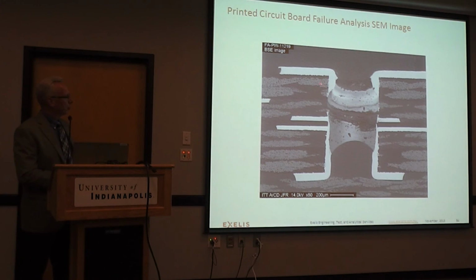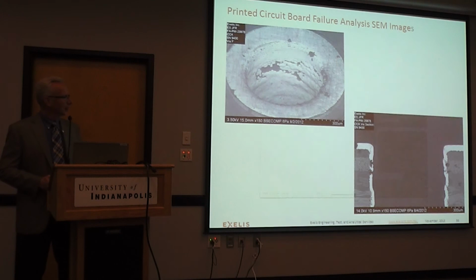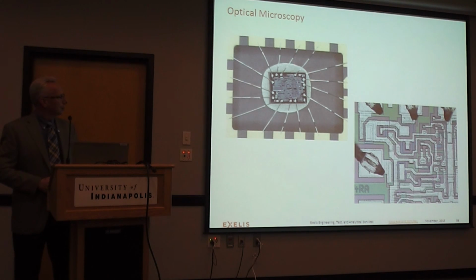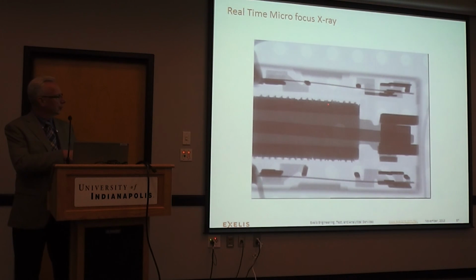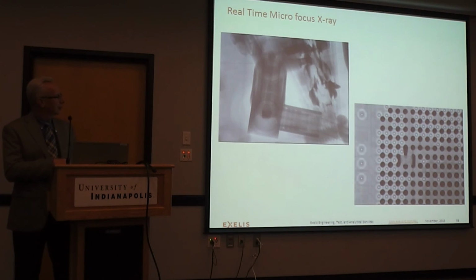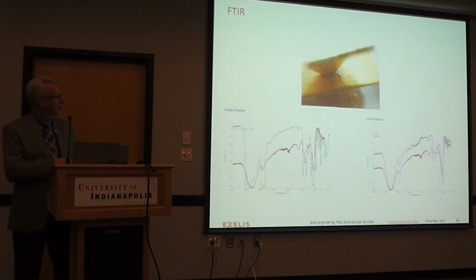And our friend the circuit board, plated-through hole: there's a circumferential void created during the circuit board fabrication process. Chemicals got into an area that should not have been exposed to the chemicals, ended up etching away the copper, and an open resulted. And here's another type of circuit board defect where you can see a void in the plated copper. Poor quality. You can now see that same area in cross section. There's an IC die. Here's a relay. Lots of good stuff there.